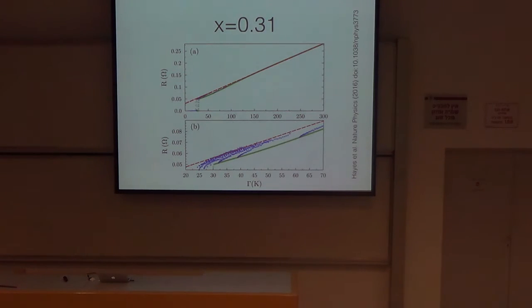All of the resistivity curves as a function of field and temperature tend to appear to asymptotically approach this linear line, which is just a statement of the fact that the B-linear resistance is the same coefficient as the T-linear resistance. These are different temperatures? Exactly, yeah. So that's how you know that it's the real deal.